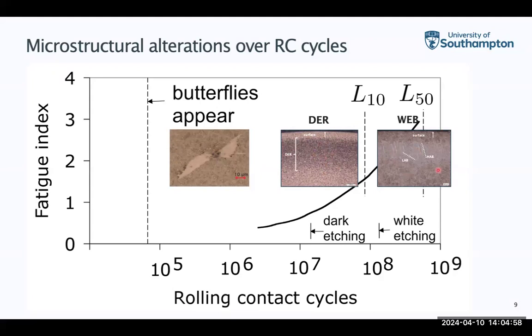And also the white edging bands, including both the low angle band, which is 30 degrees towards the surface, and the high angle band, which is 80 degrees towards the surface. So what we have found in the recent study is that the dark edging region can form as early as 5 million cycles, and the white edging bands, including the low angle band, occur just after 100 million cycles, and high angle bands occur just after 500 million cycles. So these are all from the recent study we carried out.